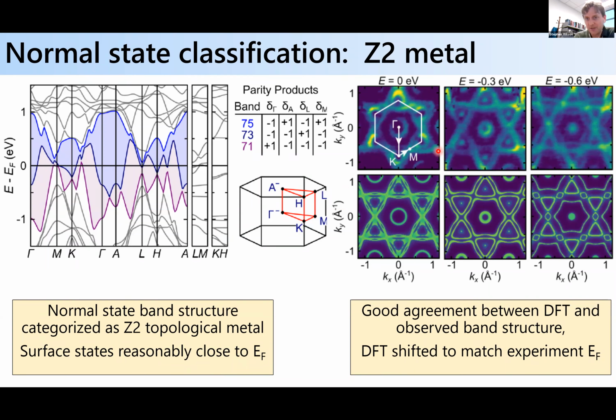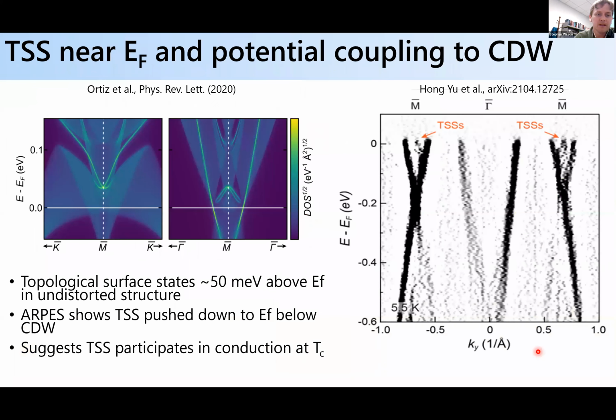And then here are the initial photoemission measurements on cesium vanadium 3 antimony 5 done by Junfeng He. Basically just benchmarking the photoemission data to the DFT calculations done by Sam Teicher, showing that DFT agrees very well with the observed band structure. And again, the DFT model was shifted, a rigid shift, to match the experimental Fermi level. Okay, so if you look at the surface state spectrum and you calculate it, Sam was able to identify surface states that are reasonably close to the Fermi level at the endpoint, about 50 millielectron volts above.